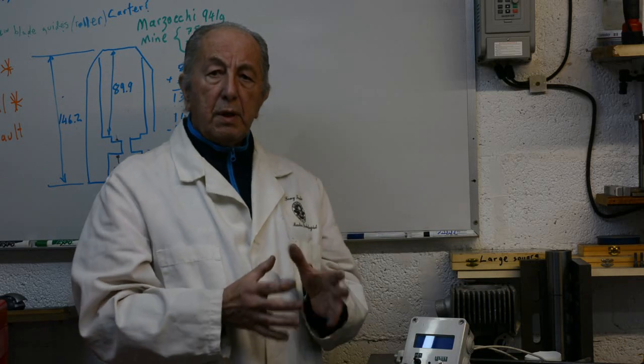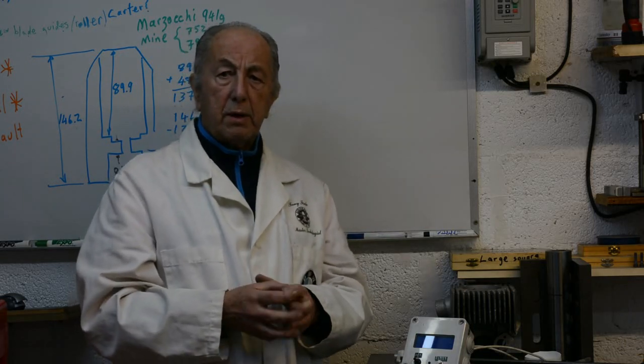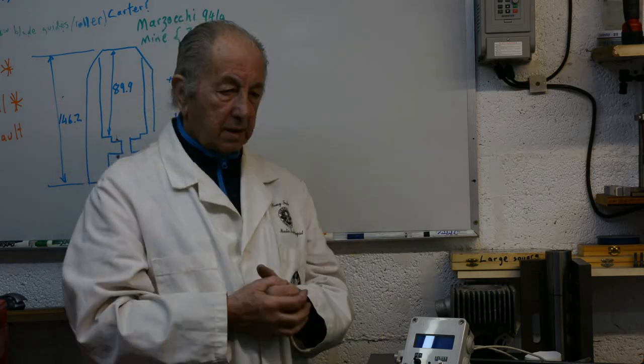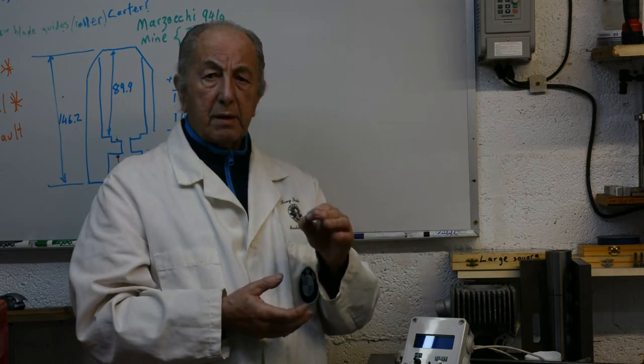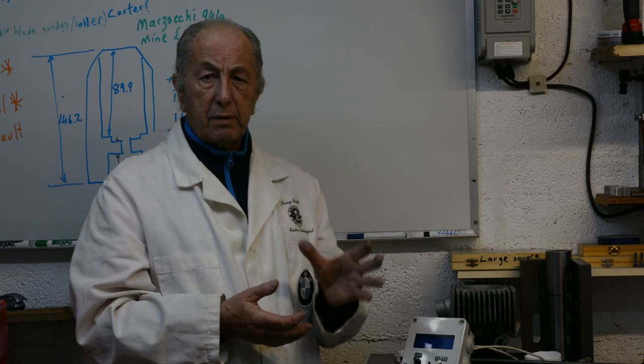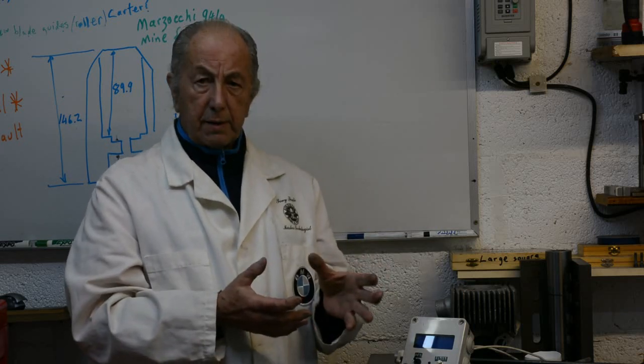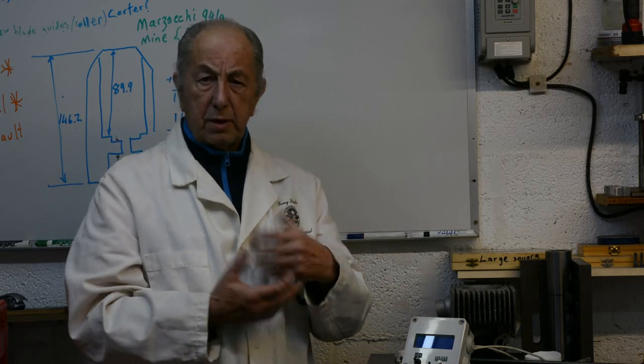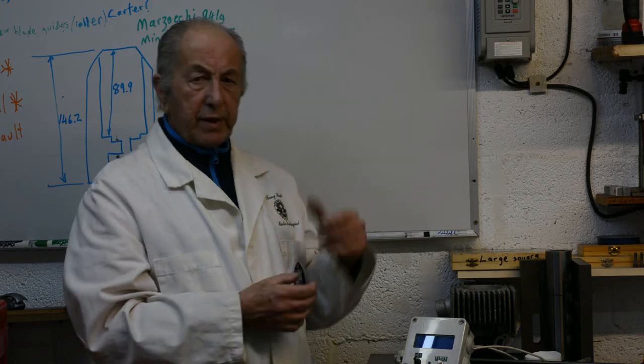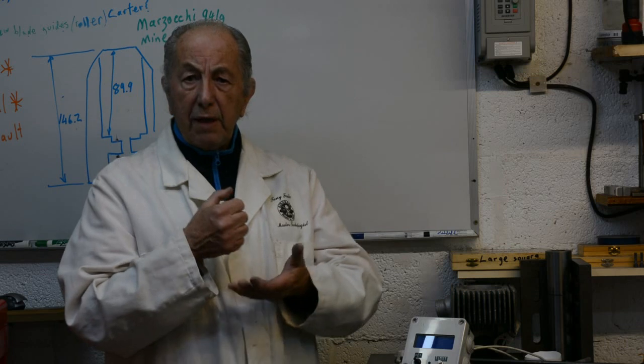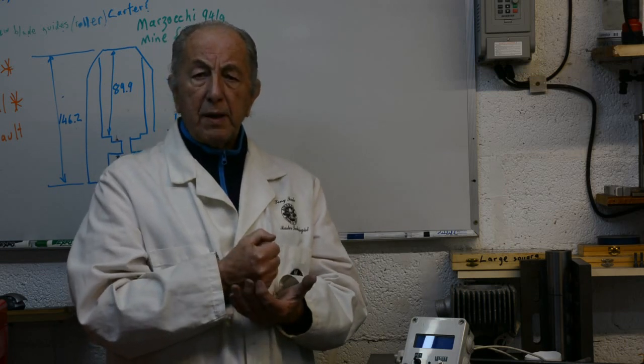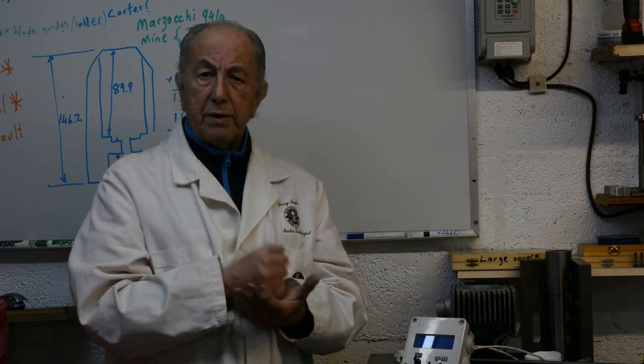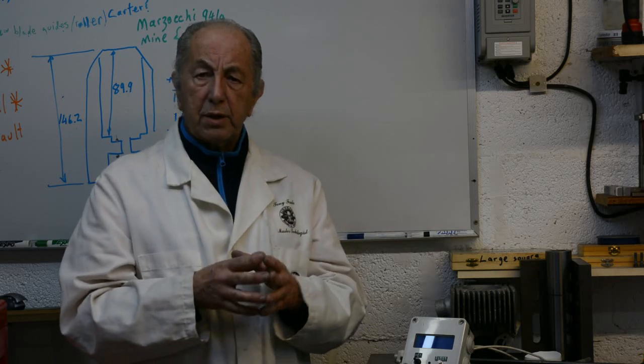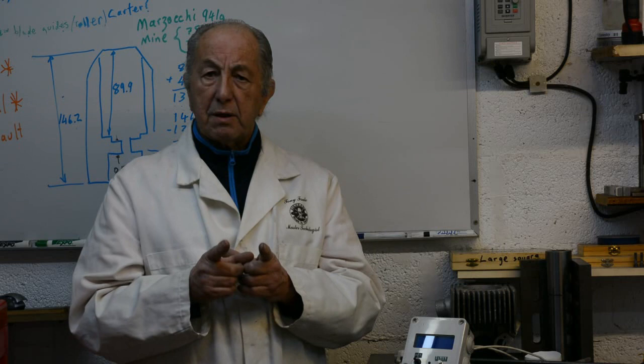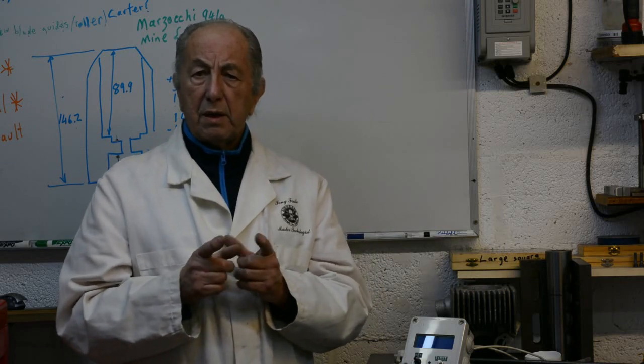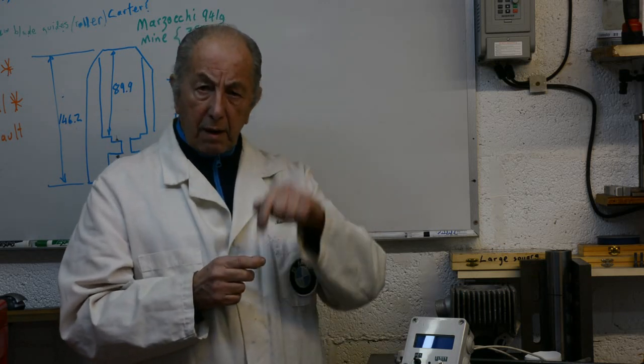It wouldn't be too difficult to make a machine that worked very much like the Rockwell hardness tester or the Brinell one. With the Rockwell machine, it's a matter of applying a certain load, and the loads are defined depending on the actual Rockwell scales you're using, and the depth of indentation is measured. That's measured with some form of dial gauge. The Brinell system, on the other hand, uses a much heavier force. It forces a ball into the material, but it doesn't measure the indentation depth. You then have to use a microscope or something similar to measure the diameter of the indentation that's left. Now you can imagine that that's a lot slower and less precise than the Rockwell idea of actually measuring the